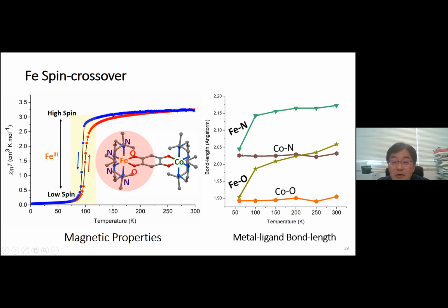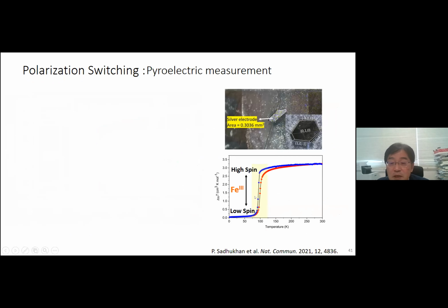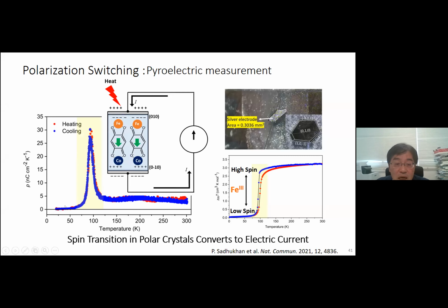And this spin transition is confirmed by a metal-ligand bond length change from single crystal analysis. And furthermore, this change is detected by X-ray absorption spectroscopy, iron site change as shown here. And we measured the pyroelectric property of this spin transition behavior using this single crystal. And this is the result. As you can see, a large pyroelectric current is clearly detected at the spin transition temperature, 90 Kelvin. So this means this compound exhibits polarization switching. The origin is spin transition, as shown here.